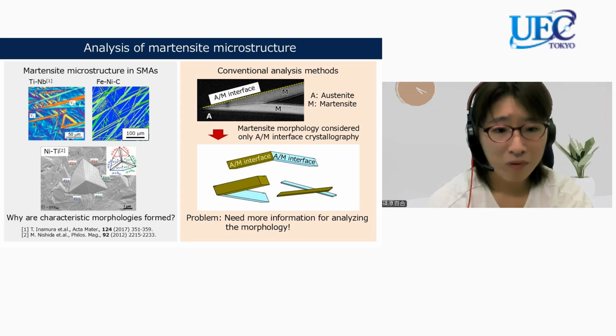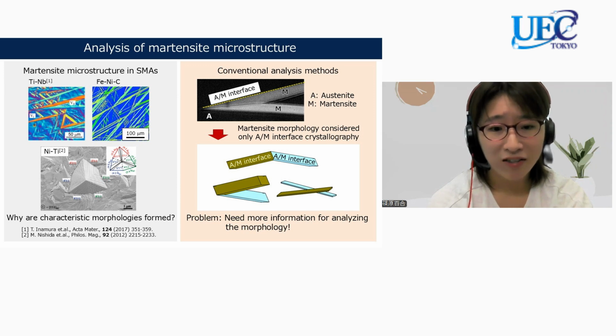However, conventional crystallography has limitations. It primarily focuses on the interface between austenite and martensite, which cannot determine the specific morphology formed. For example, the three morphologies shown here have the same austenite-martensite interface.